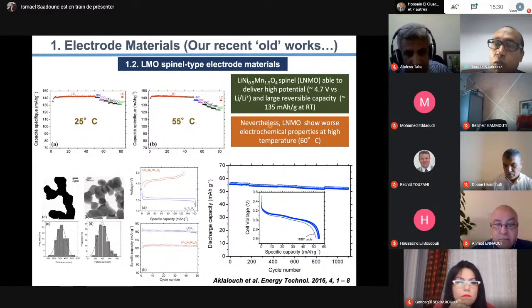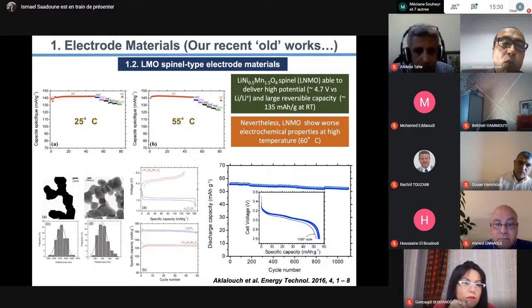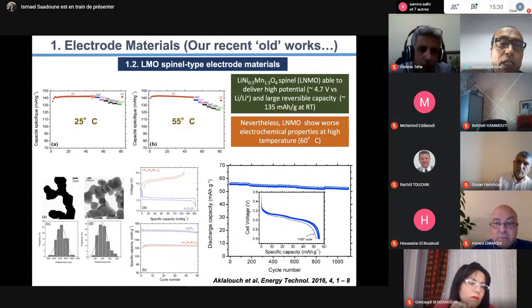So what we do at that time is replace a small amount of manganese with another element. Here you see we have the performance at 25 degrees and 55 degrees. This is cycling properties at 1C, and we have exactly the same properties at higher temperature.